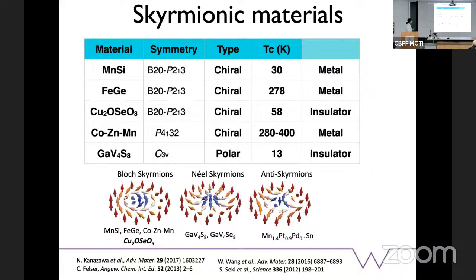were manganese silicide, closely followed by the iron germanium and the copper oxyselenite. Now, if you look at these most well-studied of the skyrmion materials, one thing that you will see that's common between all of them is that they're all chiral space groups, and this gallium vanadium 4 sulfurate is a polar space group. And most of them in the beginning tended to adopt the B20 or the P213 crystal symmetry. So there was a lot of search going on for new skyrmion materials in this specific symmetry or space group. And then it was followed by the discovery of these two materials.